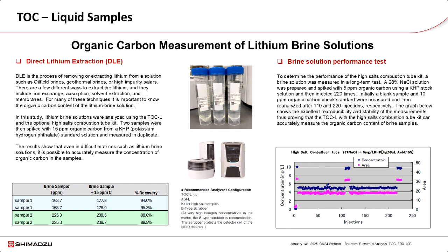The percent recovery of the added 15 ppm organic carbon was within 12% of the actual value, proving that the instrument can accurately recover organic carbon in lithium brine solutions. The replicate measurements of the spiked solutions were nearly identical, indicating that the measurement of the lithium brine solution is also reproducible. We did another study to test the long-term performance of the TOCL measuring brine solutions.